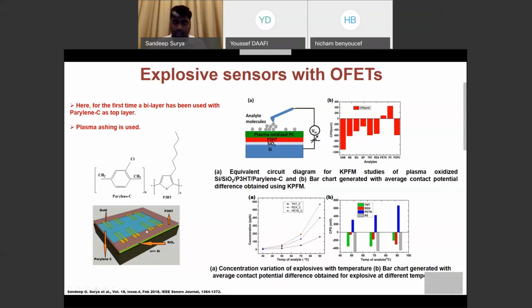So further, what we did is parylene C was already explored at that point of time for opening up dangling bonds when you do the plasma etching on the top, and the contact angles were really high after the process of plasma etching, and the material readily becomes interactive and it starts interacting with different analytes. So we thought, why not use, apart from making an OFET, here in this case with the plasma etched OFET, it was detecting RDX and TNT without any problem. But further, we thought of studying the surface based parametric analysis, physical parametric analysis, by making use of Kelvin probe force microscopy.